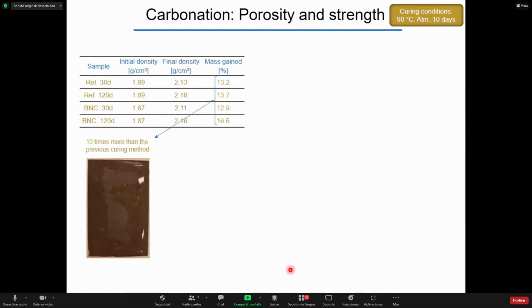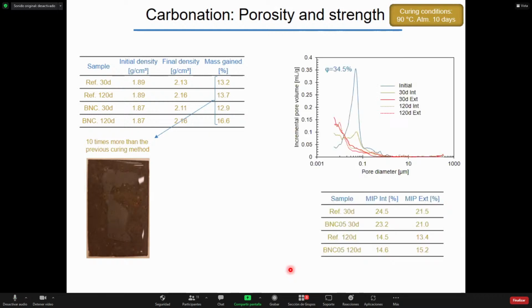When we carbonated these samples, we saw that the carbonation was 10 times higher than with the previous curing method. We also took the capillary porosity in the interior and the exterior as before, and we saw in this case that the porosity was reduced to 14%, and no contribution of bacterial nanocellulose was seen.